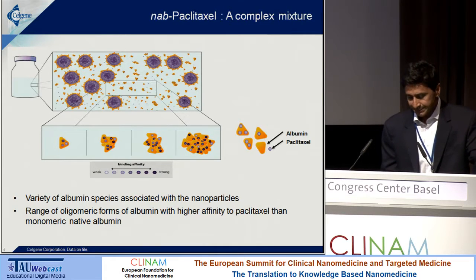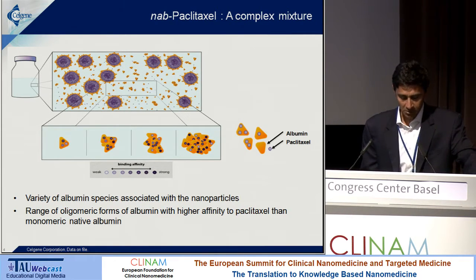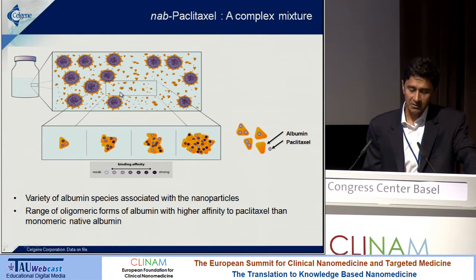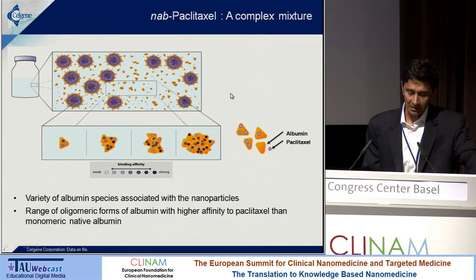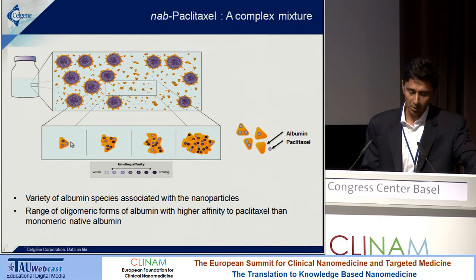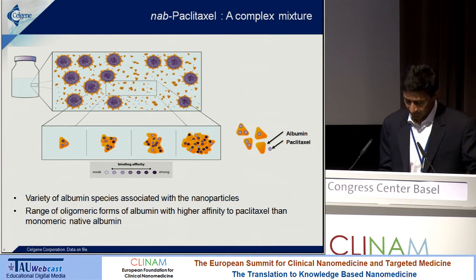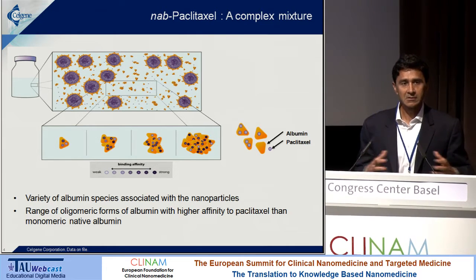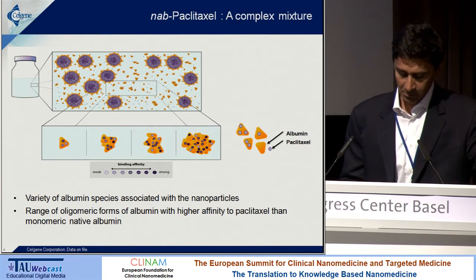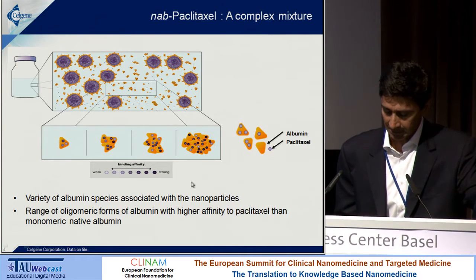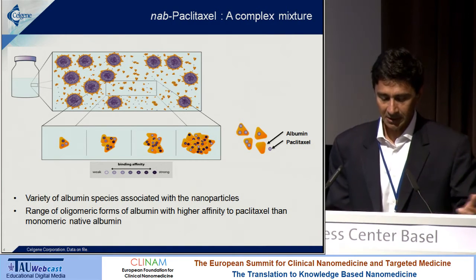What's in the vial? You have the nanoparticles, of course, which are of a specific size range, roughly around 130 nanometers, but in addition to the nanoparticles with their coatings, you also have different albumin species — and this is where the complexity arises. You have different albumin species that are cross-linked into different oligomeric forms: single albumin as monomer, dimer, trimer, oligomer, or polymer. The paclitaxel is bound to the albumin, and each albumin can bind many different paclitaxel molecules. As you increase the size of the oligomeric or polymeric species, the affinity for paclitaxel changes because larger polymers can have a higher affinity.